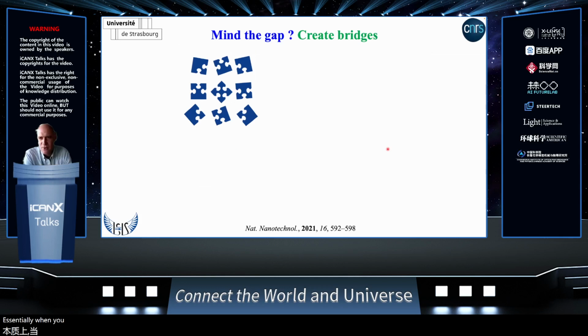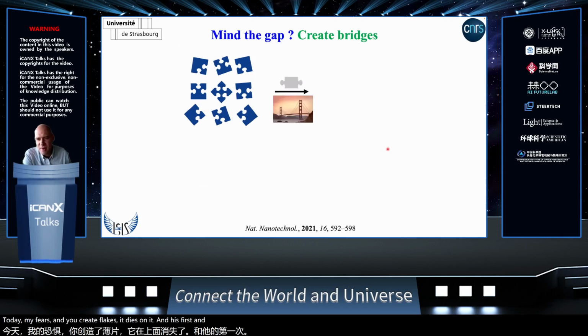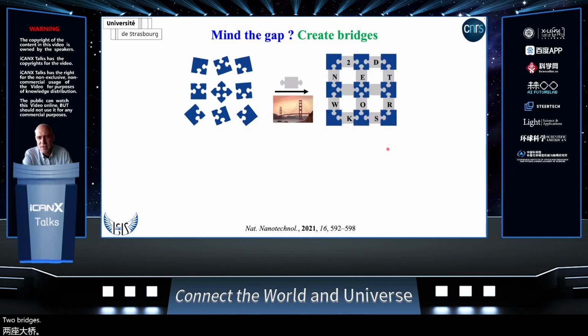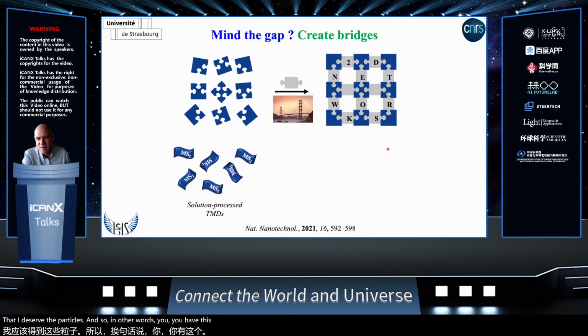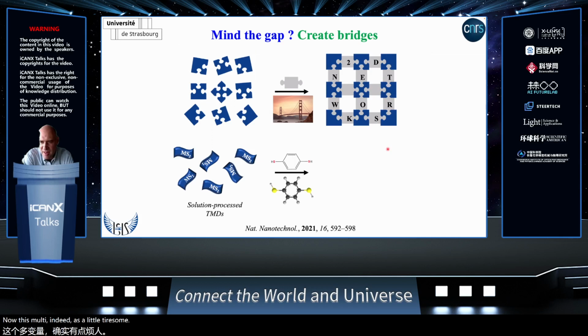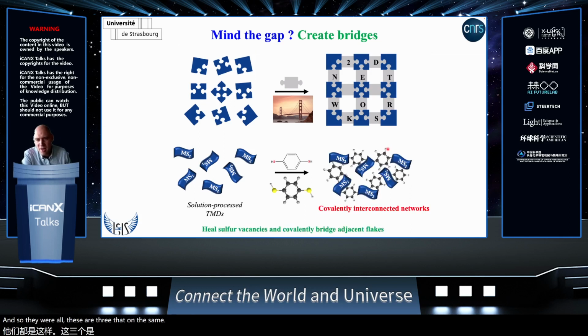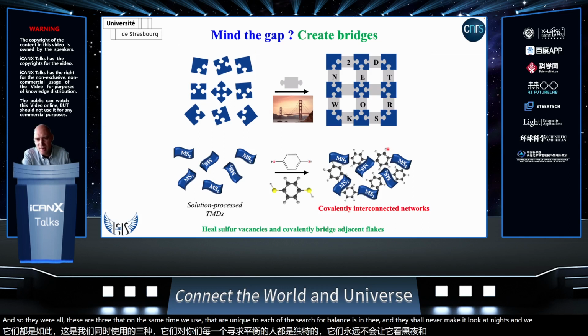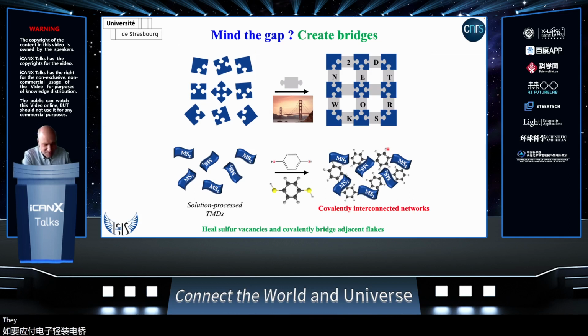Essentially, when you exfoliate 2D materials as an ink, you create flakes that are isolated and dispersed. Therefore, the goal is to find a way to bridge these flakes with the right piece of the puzzle. So you have these flakes of, for example, MoS2 or tungsten disulfide or rhenium disulfide, and you combine this with the doubly thiolated molecule that acts as a bridge. This molecule has the two thiols in the para position and a conjugated bridge that can be used for charge transport. The goal is that at the same time, we use the thiol unit to heal the sulfur vacancies in the transition metal dichalcogenides, and we use the conjugated electronic nature of the molecule to covalently, electronically bridge the adjacent flakes.